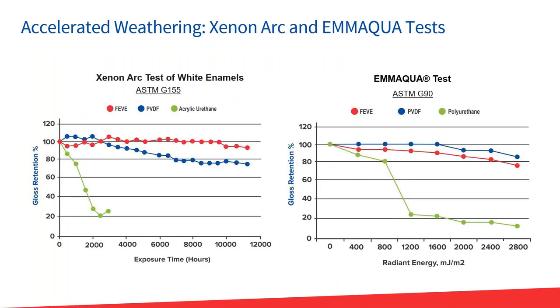Another method is xenon arc, and then there's this Q-Sun test. There's another company that has a test called Q-Track. They're not the same, but they are somewhat similar in how they test. On the xenon arc, which is on the left, you're looking at a FEVE, PVDF, and then again, a conventional acrylic urethane. This is another chamber, different set of bulbs, tracks the sunlight, and you can see here 12,000 hours with the FEVE and PVDF, really good gloss retention versus the acrylic urethane.